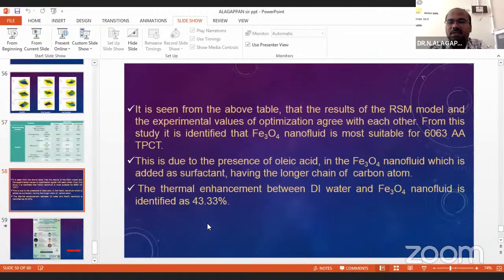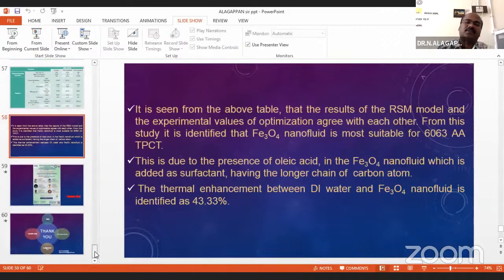So it is seen from the above table that the results of the RSM model and the experimental values optimization agree with each other. From the studies, it is identified that Fe3O4 nanofluid is most suitable for 6063 AATPCT. This is due to the presence of oleic acid, the surfactant in Fe3O4 nanofluid, having a longer chain of carbon atoms. The thermal enhancement between DI water and Fe3O4 nanofluid is 43.3%.